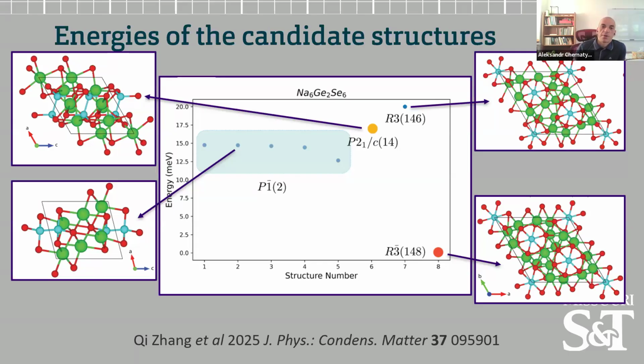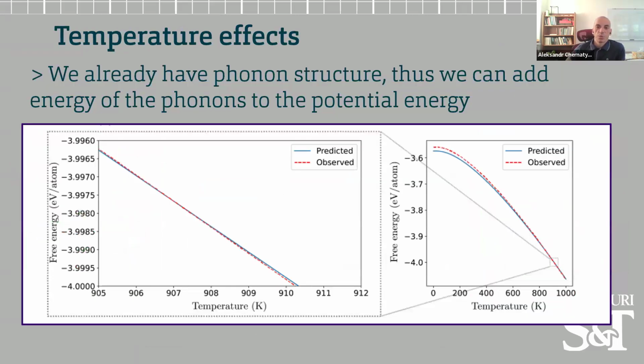In this particular case, however, we do have a little bit of the explanation why it might be so that experiments found the different structure, because we can add the phonon energy to the system to calculate the free energy of the system, which now includes phonon contributions. And if we do so, we see that the free energy crosses over at about 900 degrees Kelvin. And the sintering temperature for many of these compounds is somewhere in this range.